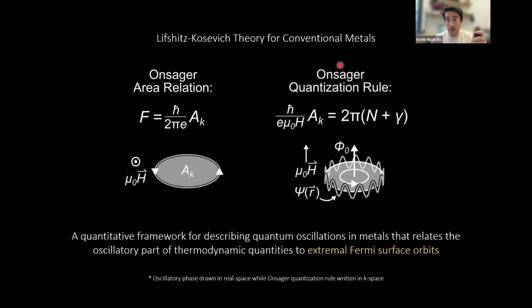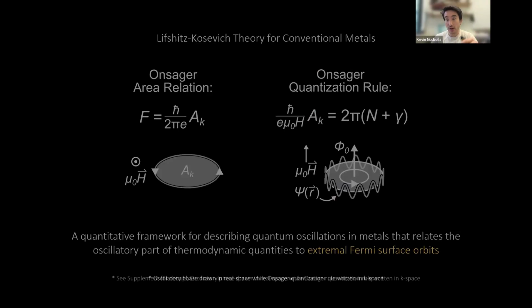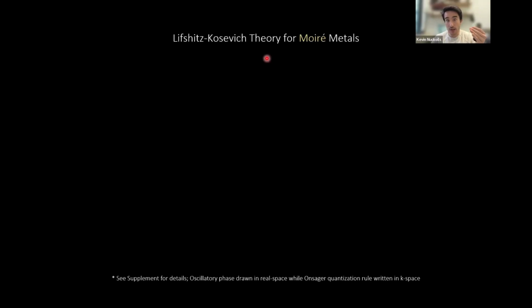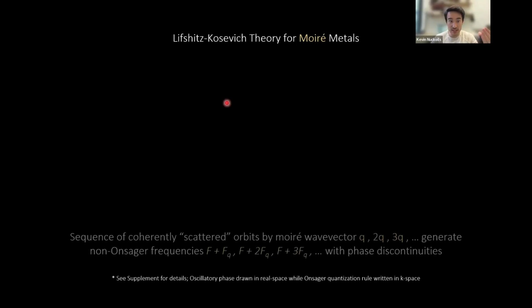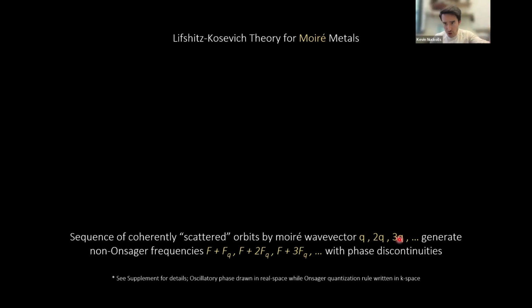So these types of rules are known in conventional metals, and our theory colleagues at MIT understood that you could actually make calculations for an incommensurate 1D modulation in our Moiré metals. So what they found rigorously through Lifshitz-Kosevich theory is that there are a sequence of coherently scattered orbits that scatter by the Moiré wave vector Q, 2Q, 3Q, integer multiples of Q, and this generates a non-Onsager set of frequencies